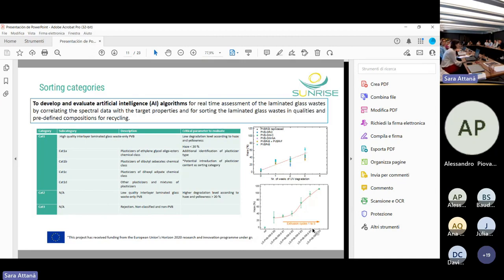We have identified that the multi-sensor tool will be able to identify category one, a high quality laminated glass waste, which will be PVB. We'll identify that this is PVB, and in addition, that this is high quality. The criteria of quality has been done according to haze and yellowness. Both will give similar results. So we have identified haze as a faster measurement, and we have set a threshold of haze below 20%.